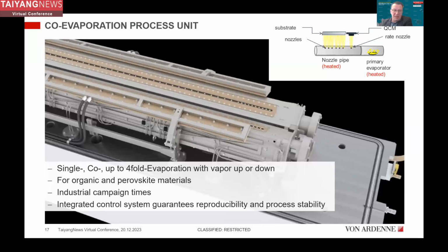There are a lot of challenges for this, and for sure the damage-free or low damage coating is one thing, and the coating of the perovskite is another thing. And here's an example of this perovskite coating. You see here a co-evaporation linear source, where 2 different materials can be coated together. On the top, you see the basic principle. You have a primary evaporator, which is heated, and then a nozzle pipe, and through the nozzles, the material is transported to the substrate, in either a coating up or coating down configuration. Both are possible. And the question is now, you can do it in 1, 2, or even up to 4-fold evaporation with our special design.